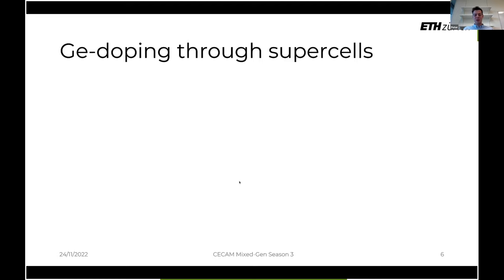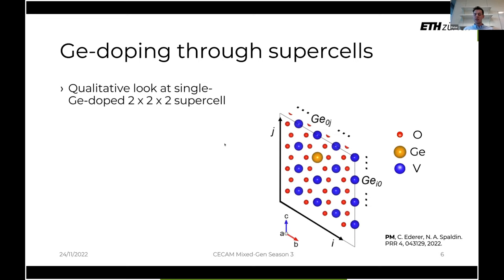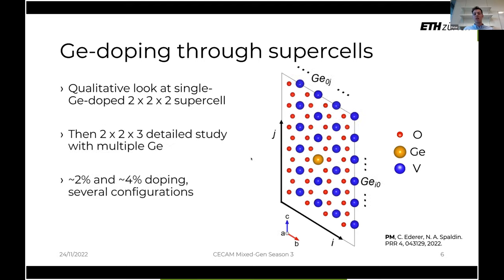And so the way we model a vanadium dioxide system with germanium substitution is by way of supercells. As a first stepping stone, we construct a relatively small supercell, the size of a 2x2x2 monoclinic lattice. Here we have a view along the A direction. So vanadium chains go along C as always. After this qualitative look, after observing some interesting things, we then go into a larger supercell, which extends in the C direction. We try to have a more detailed study with multiple germaniums in the cell, having different relative configurations of the germanium within the cell, with also various doping configurations, and trying to draw some quantitative conclusions as well.